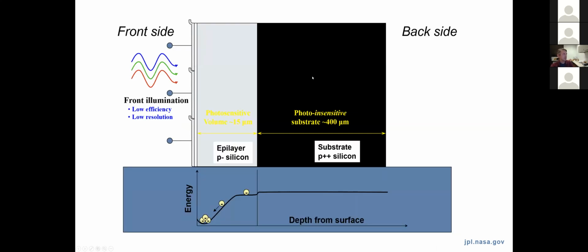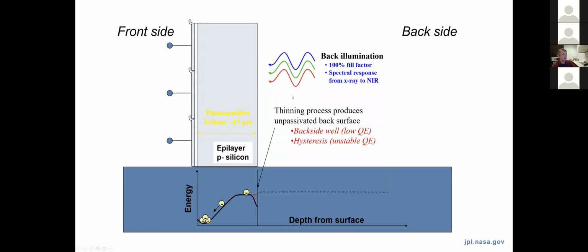So here's maybe a more intuitive way to describe the overall process. Again, if you take a cross-section of a CCD or CMOS imager, you have your contacts and electrodes on the front side. You have the photosensitive volume, which was described in detail by Roger's talk a couple weeks ago. And then typically a thick photo-insensitive substrate on the backside of the wafer. So front side illumination won't work for the UV, which we described. If you want to illuminate from the back, you generally need to remove most of that insensitive thick silicon wafer. So there are thinning processes involved in the fabrication of these devices, but you're still left with this dead layer at the back of the device. So again, you'll lose charge carriers generated right at this backside.